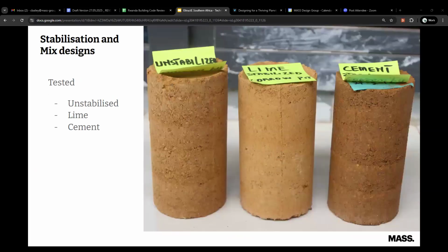For the mixes, we tested samples using either stabilization of cement and lime, and samples with no stabilization at all. And we did test about 5% to 7%. In the end, we realized that with 5%, we could get almost all the properties that we wanted, but we were not achieving the protection that is required, especially during construction. So we upped the stabilization using cement up to 7%. But even with that, with 7% cement stabilization CSEBs, we still had a 73% reduction compared to a fired brick.